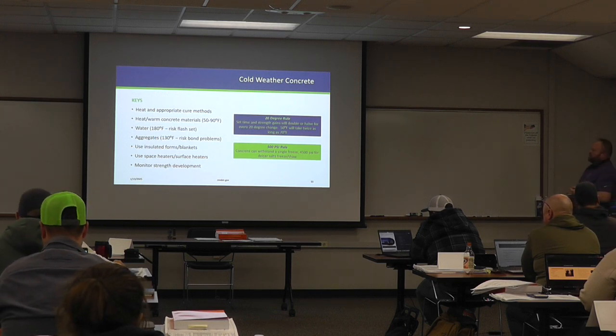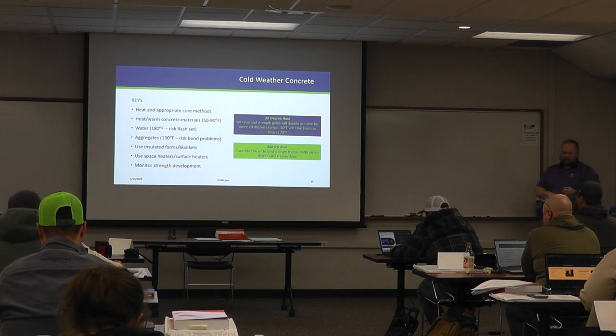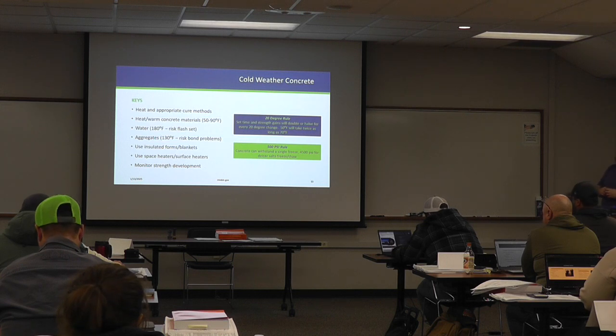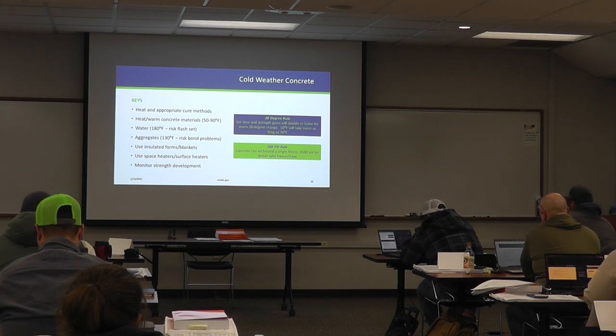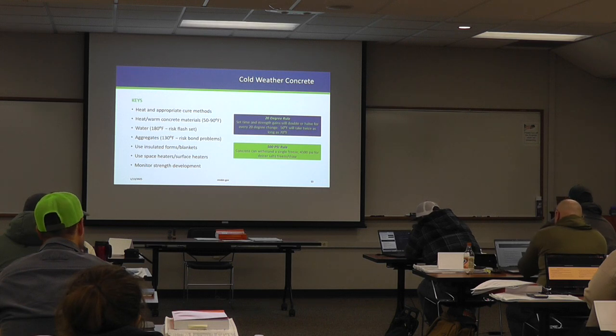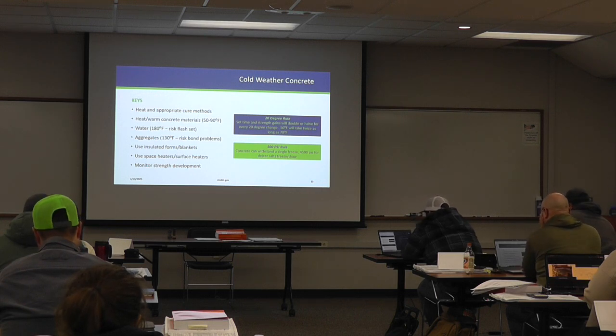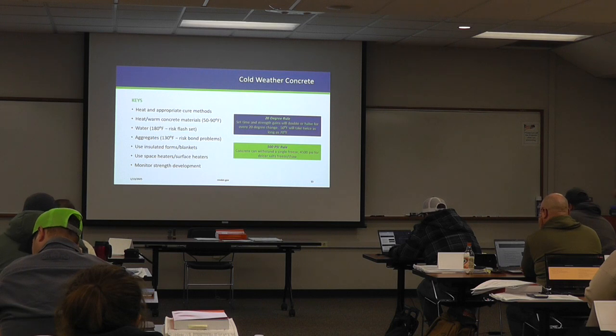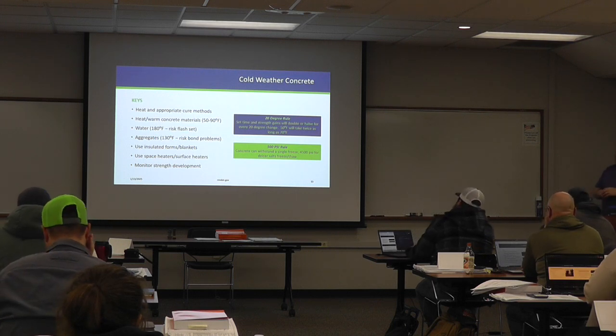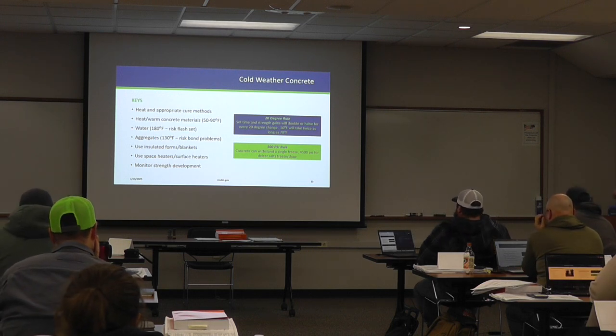Our aggregates, if the producer is heating the aggregates, we don't want those to be above 130 degrees because then we could risk some bond problems between the paste and the aggregate. We also want to use insulated forms or blankets to take advantage of that hydration reaction and keep that heat in, just like we wear a coat outside. Using space heaters or surface heaters, again, make sure that those are exhausted out of the area if you have housing and heat for them. And then we also want to monitor that strength development, because that's what gives us our freeze-thaw resistance: the stronger the concrete is.